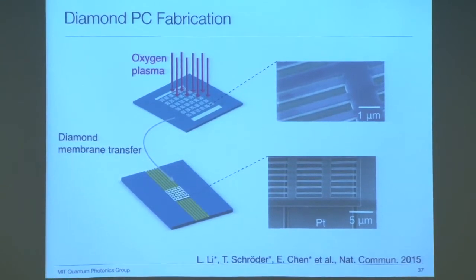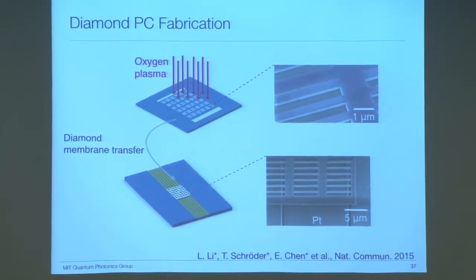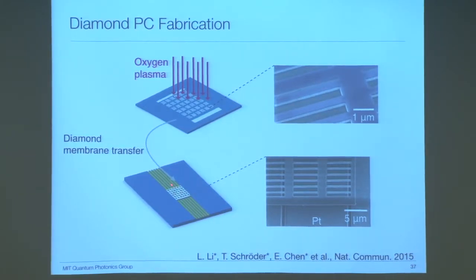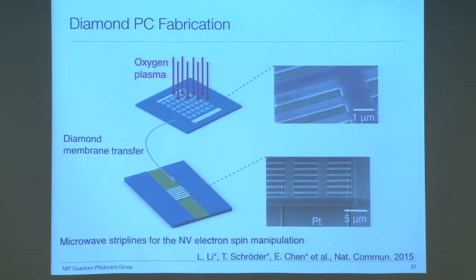transfer, which is a method that I previously introduced. And this is a diamond membrane on top of a new silicon wafer. And the silicon wafer has ridges of silicon that act as spacers for the diamond membrane, so that these diamond membranes are suspended in air 2 microns from the bottom for cavity measurements. And in the recessed regions, platinum is deposited, which serves as a microwave strip line for coherent spin control.